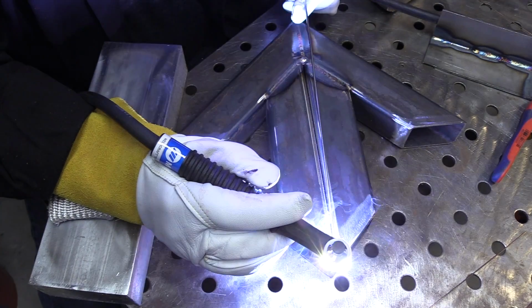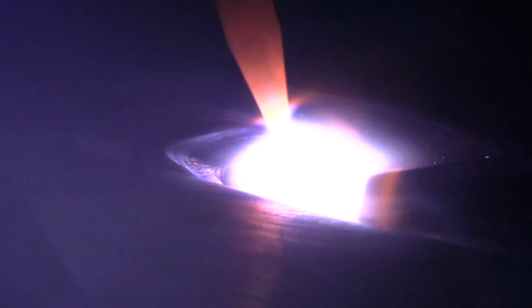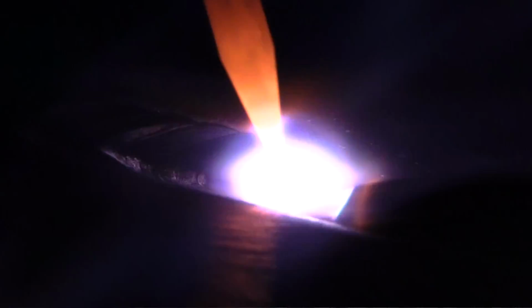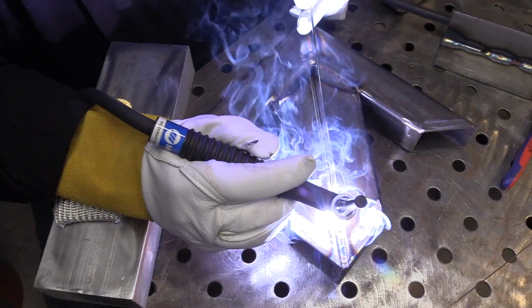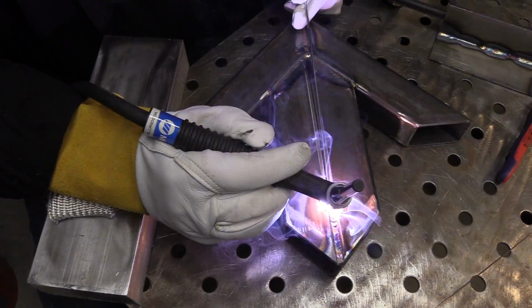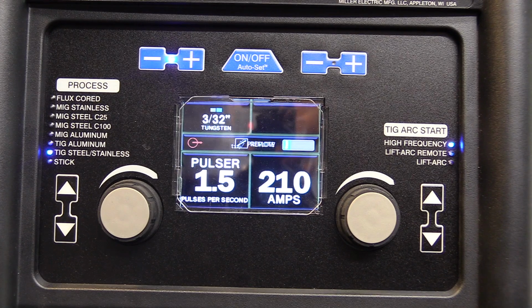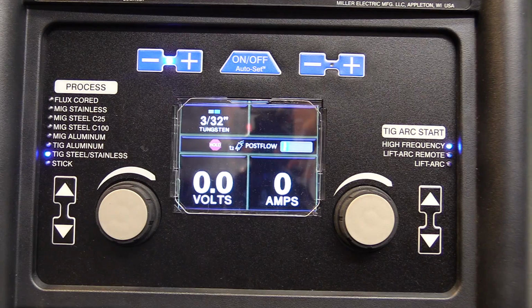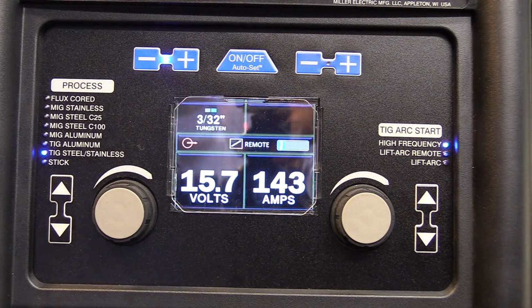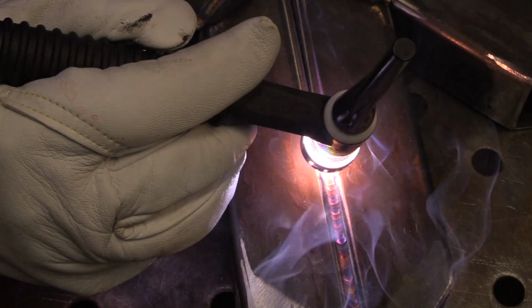So again, 1.5 pulses a second. The machine is set pretty much maxed out. I'm not quite full pedal, but I'm close. What you get when you pulse, you get an average of the background current and the pulse current. So the machine, as I'm welding here, was reading out somewhere in the 140 to 150 range, even though I was set at 210, because I'm getting a high and a low current, so it kind of averages out.